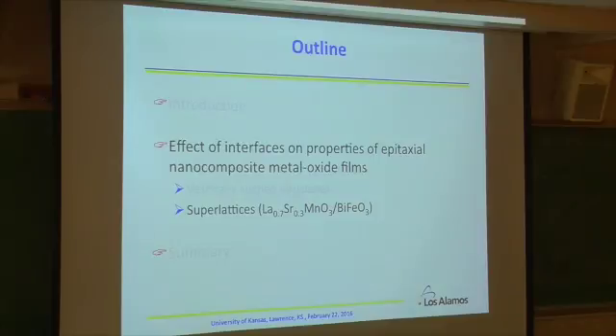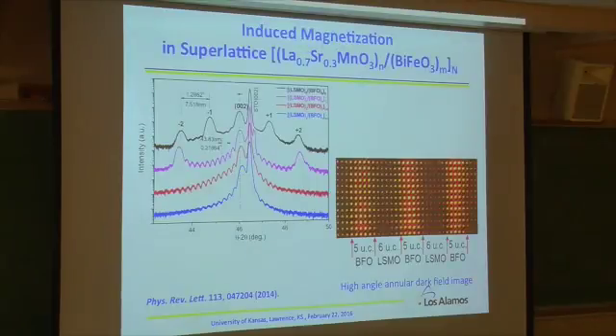So I think I will just quickly go through, probably 10 more minutes, this one. Talking about superlattices, how we do this. Here, for example, again, that's an LSMO system, working with the bismuth ferrite with this interface together. We study this kind of material. People also say, when this is ferromagnetic and this is antiferromagnetic, when you put these two together, do you have that kind of coupling effect or not?